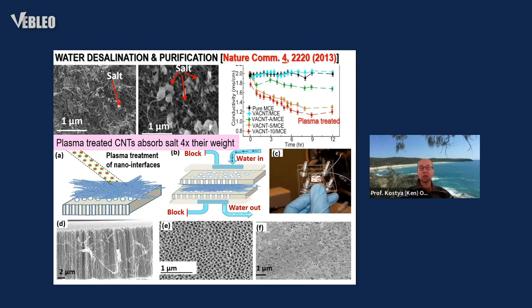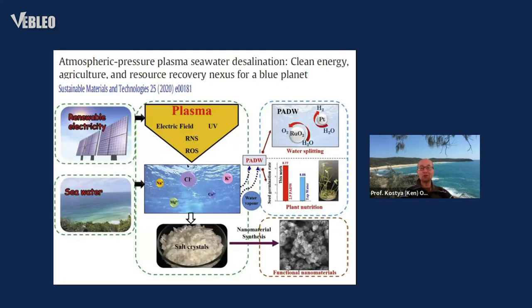A more recent example shows that we can also treat water directly. While treating seawater directly, we can not only evaporate it and separate salt crystals from the evaporated water, but the evaporated water becomes plasma-activated desalinated water. In this water, we have reactive species, as I discussed above, and those reactive species facilitate electrocatalytic processes, in particular the water splitting reaction, if you use plasma-activated desalinated water as electrolyte. If we utilize it for germination and growth of plants, it accelerates the germination and plant growth processes.